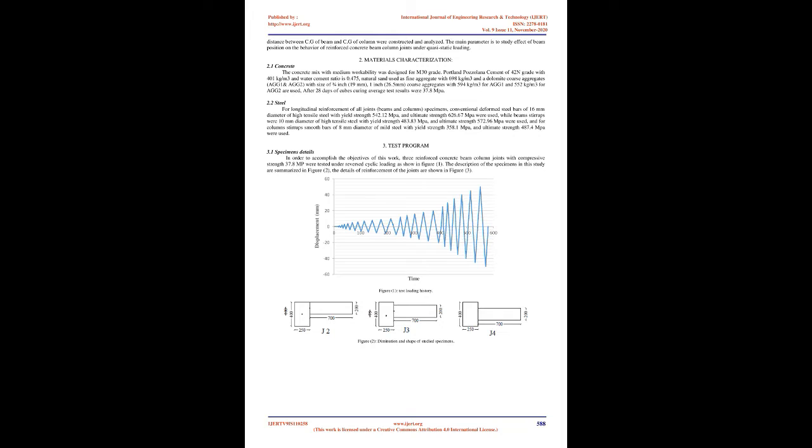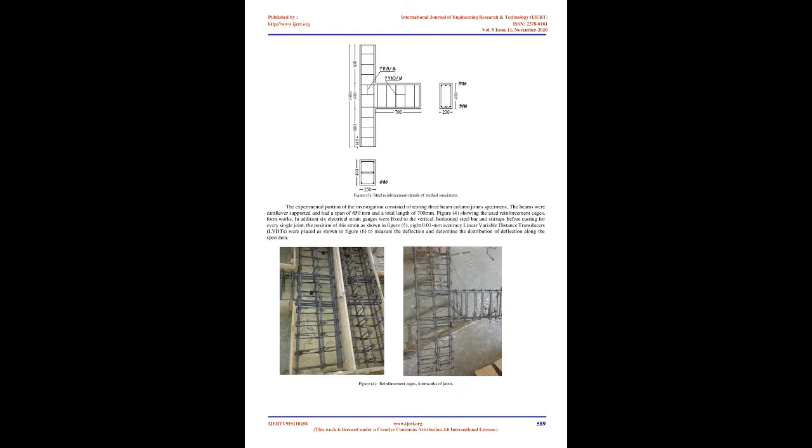The earliest test conducted by Abram indicated that compressive strength of concrete was sensitive to the rate of loading. Since then, numerous experimental studies investigated dynamic mechanical properties of concrete over a wide range of strain rates. Atchley and Furr, using cylinders, found that compressive strength and energy absorbed increased with loading rate, becoming constant at higher rates. Bischoff and Perry, and Malvar and Ross, summarized the effect of loading rate on concrete compressive and tensile strength respectively.